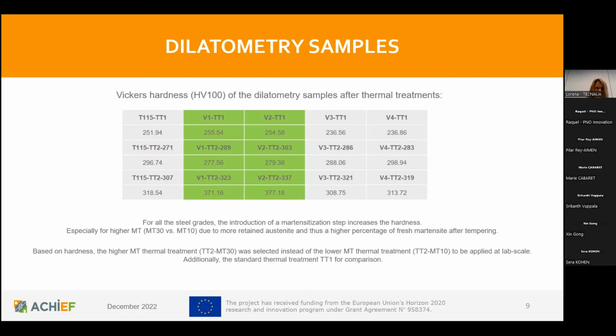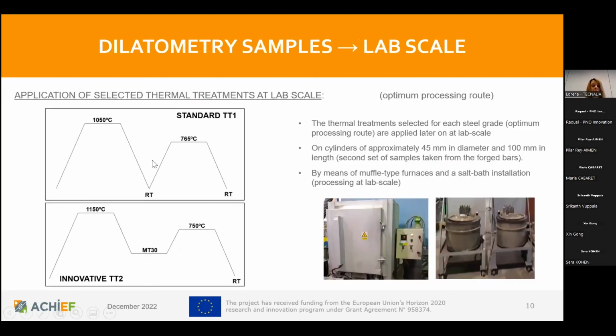Based on hardness values, the higher MT thermal treatment, that is TT2 MT30, was selected instead of the lower MT thermal treatment, TT2 MT10, to be applied at lab scale. Additionally, the standard thermal treatment, TT1, was applied at lab scale to all steel grades for comparison. So we have selected these two thermal treatments, the standard one and the innovative one with MT30 temperature. And these selected thermal treatments are called the optimum processing route and applied on the steel grades at lab scale.